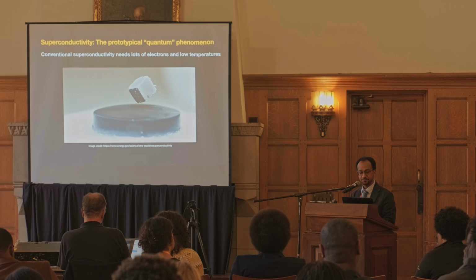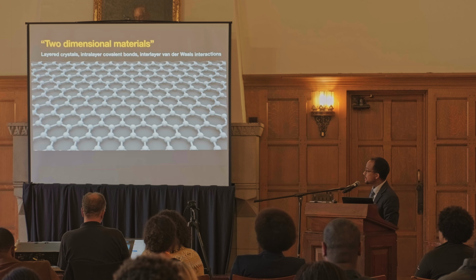So there's been a real search for unconventional superconductors. One of the most exciting classes of materials for unconventional superconductivity is a group of oxides, the copper oxides, the cuprates, which were discovered in the 70s and 80s and still have the highest temperatures at which they become superconducting. But we still don't understand the mechanism by which that happens.